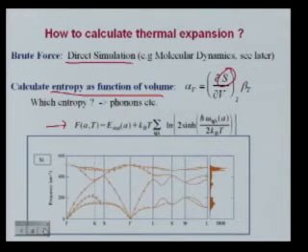Remember that to get the thermal expansion, it's not enough to just do the phonons at one volume, because you need to get the entropy as a function of volume, so at a few different volumes. So you really have to do the phonons at several different volumes to get the thermal expansion right. This sort of looks hard, but phonon calculations have become quite routine. They're very well developed. There are in some cases even codes that do it almost semi-automatically.